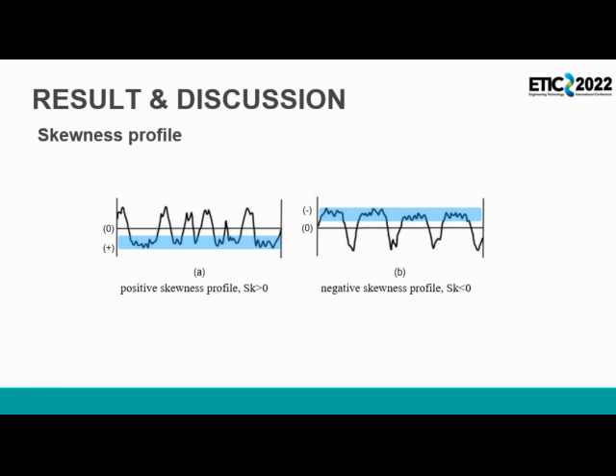The values of skewness describe the degree to which the roughness form is biased. Skewness is a useful tool that can be utilized to efficiently characterize the contour of the surface texture height distribution. If a surface height distribution has a symmetrical form, then the surface skewness value will be equal to zero.